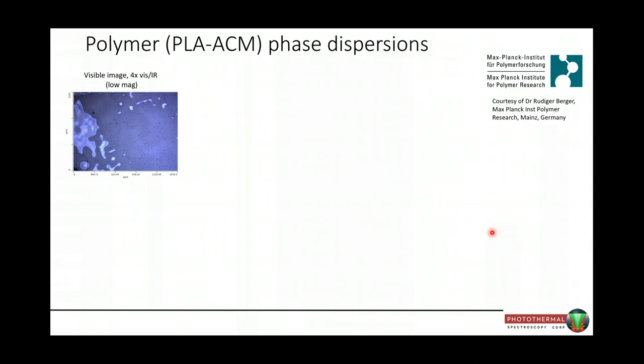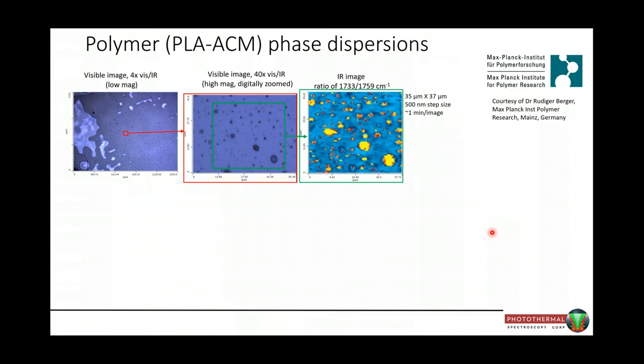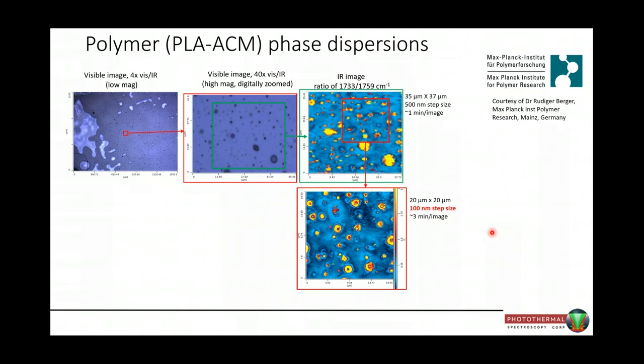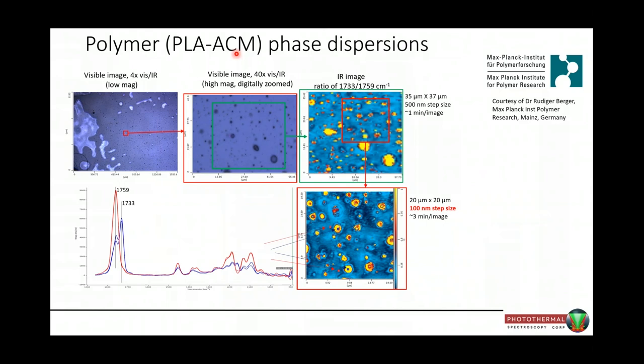This is a recent example from Rudiger Berger at the Max Planck Institute in Mainz, who provided samples of PLA blended with ACM phase dispersions. You can see the visible image, and we can go in and collect IR images and ratio the images collected at 1733 and 1759, which are the PLA bands. And then we can step even finer down to 100 nanometer steps, and in 3 minutes we can collect these images, and we can get identifiable spectra from the two domains that clearly distinguish the ACM and the PLA.